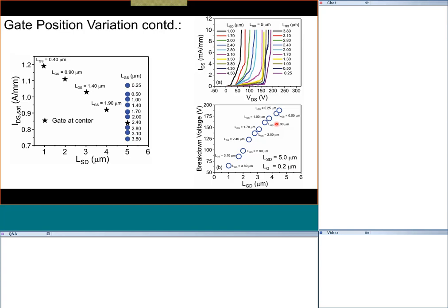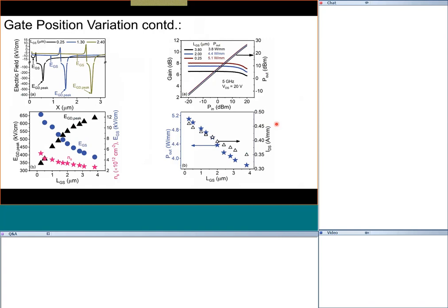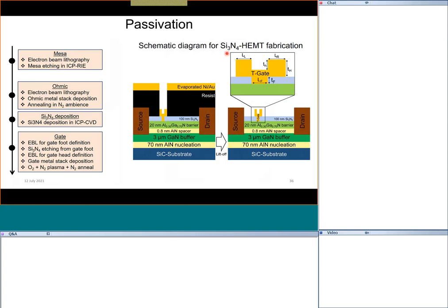We found a power output of 5.1 W/mm at just 20 volts. If you increase the voltage, you get further power. There are other mechanisms to increase power, such as field plates, which increase the operating voltage as well as the delivered power. So summarizing ohmic considerations: I've discussed contact resistance improvement and proper gate positioning between source and drain. There are hundreds of other considerations to achieve good devices.